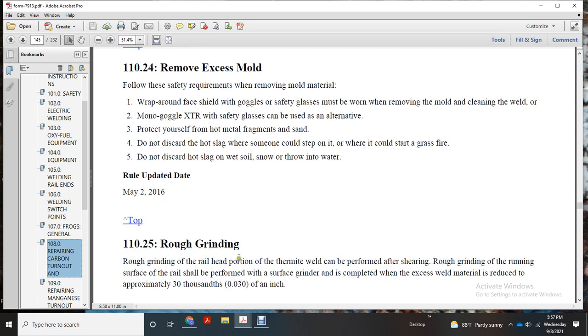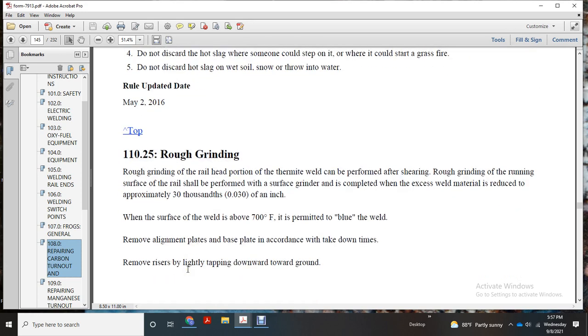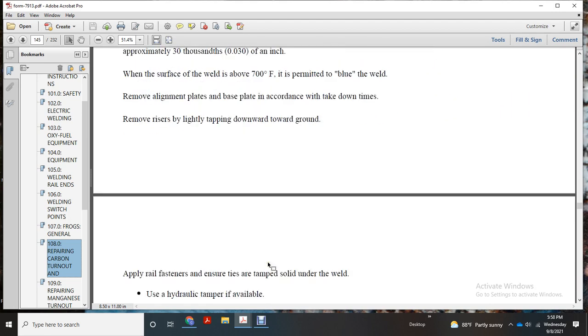Rough grinding on the railhead portion of the thermite weld can be performed after shearing. Rough grinding of the running surface of the rail shall be performed with the excess weld material reduced to approximately 30 thousandths of an inch. When the surface of the weld is above 700 degrees Fahrenheit, it is permitted to 'blue' the weld, remove the alignment plate and the base plate, and according to the takedown time, remove risers by lightly tapping downward toward the ground.